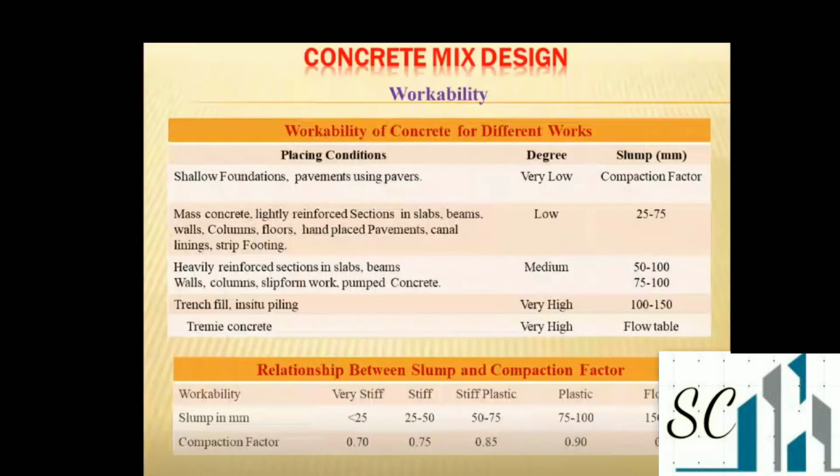Workability is depending upon the placing conditions of the concrete. If you are placing the concrete on heavily reinforced sections in slabs, then the degree of workability is medium and the slump required is 50 to 100. Like that, depending upon the placing condition, we will decide the workability.